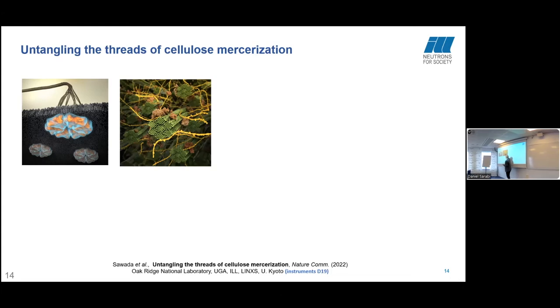And these bundles can consist of nanocrystals in which all the fibers are parallel, or the nanocrystals can be antiparallel. So within the nanocrystals, everything is parallel, but nanocrystals themselves can be up or down. And we determined this structure using, again, small angle neutron scattering. We actually determined this plant structure to understand how plant biomass can be pre-treated during biofuels production.